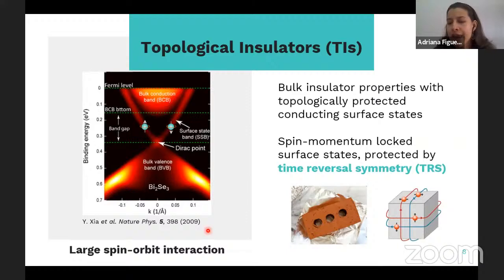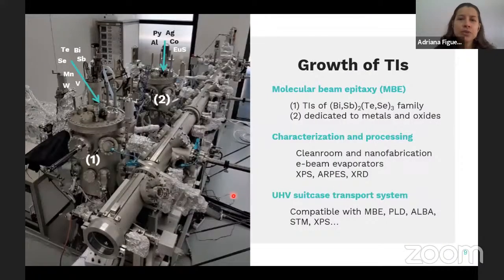Okay? And what we do at ICN2 is to grow topological insulator thin films using our machine of molecular beam epitaxy. Here I'm showing a picture of the growth chamber that we have in our lab. It comprises two growth chambers. One is dedicated to the growth of TIs of the family of bismuth, antimony, tellurium, and selenium.